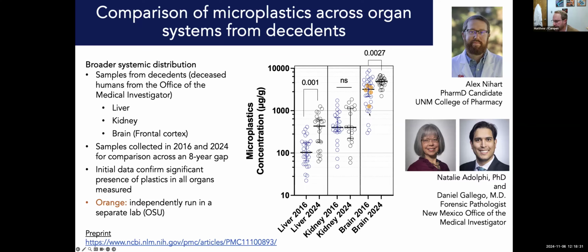First of which is that from 2016 to 2024, by and large, the microplastics seem to be increasing in concentration. This was not the case in the kidneys, but it was in the liver and in the brain. We also noticed that the brain is about 10 to 20 times higher concentration than what we see in the liver or kidney. Added to this, the little orange dots were independently run samples at a collaborator, Jorge Gonzalez at Oklahoma State, who also has pyrolysis GC capability. So we confirmed that his results were ballpark what we were seeing as well.